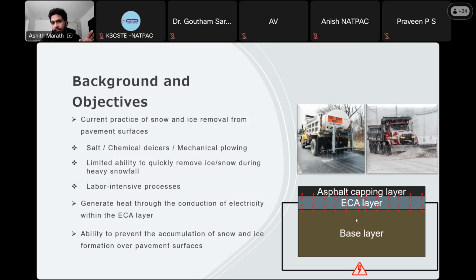On the right side, you could see the typical structure of the ECA pavement, which has a base layer as the conventional pavement, which could be unbound or bound layers, and there will be an electrically conductive asphalt layer between the asphalt surface layer and the base layer. There will be an electrical power supply to this conductive layer, and as it conducts the electricity, it generates heat and propagates towards both sides. Normally we expect more heat conduction to the upward side, because in winter seasons the asphalt surface has a colder temperature than the base layers. Because of that, more heat flow naturally occurs towards the upward direction of the pavement.